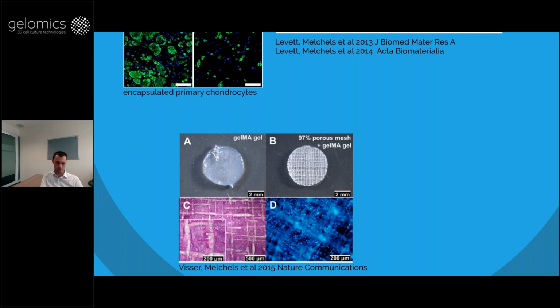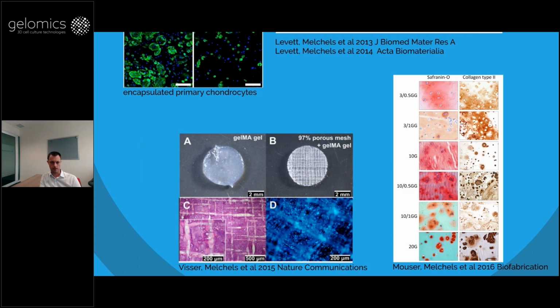So we used also the fiber reinforced gels that I talked about before. We used them with chondrocytes, and so we could still engineer that tissue, have the cells proliferate and make tissue in those gels. They weren't really affected much by the fibers. Whereas when you put gellan gum through the gel to modify the rheology, make it more printable, you see a completely different picture. So you always have to keep in mind when you improve the printability, you have to look at the effects on the biology as well, which probably then advocates for using one of those other strategies of using an internal support or suspension media, so you don't have to tweak the bioink that much.